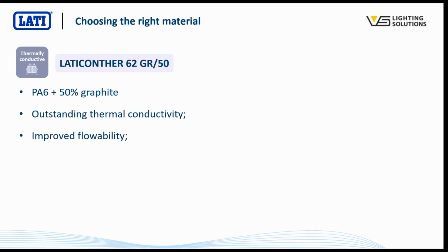It's a grade with improved flowability. So when we look at some pictures later of the part, you'll perhaps appreciate this a bit better. But for applications like this, it's quite common to have complex shapes, lots of right angles and corners in there, sometimes relatively thin sections. So good flowability is critical for these sorts of applications. We've talked about dimensional stability, and this grade is excellent for that, to maintain that good thermal contact between the heatsink and the heat source.